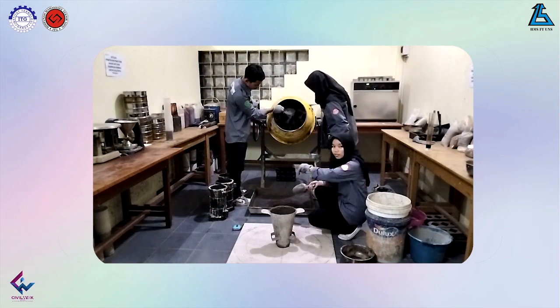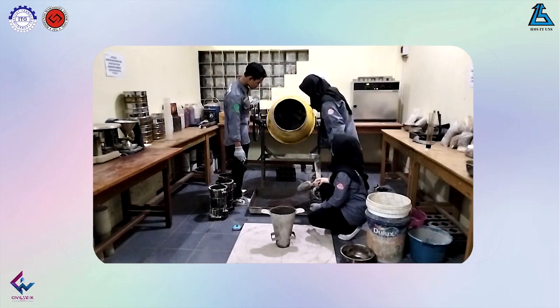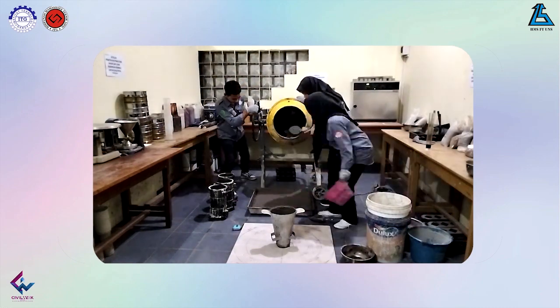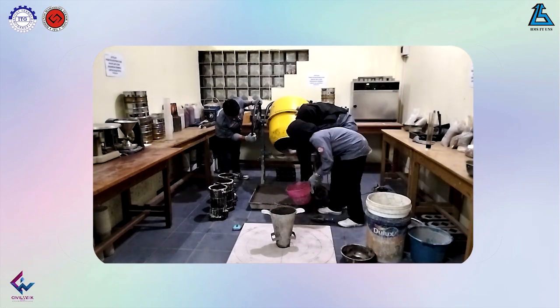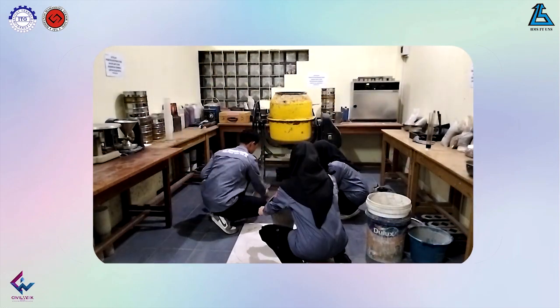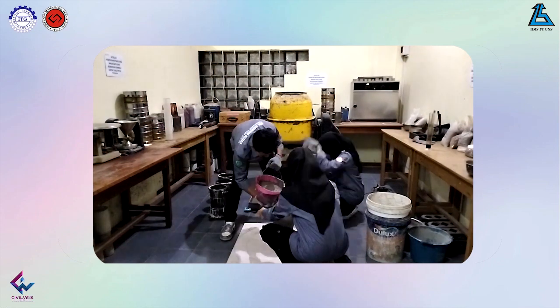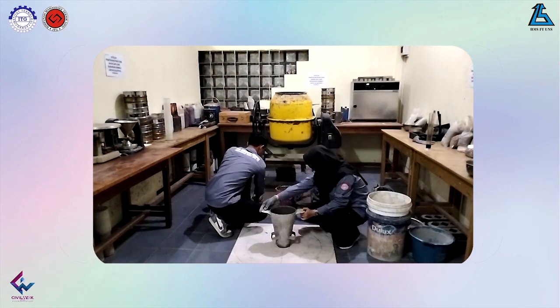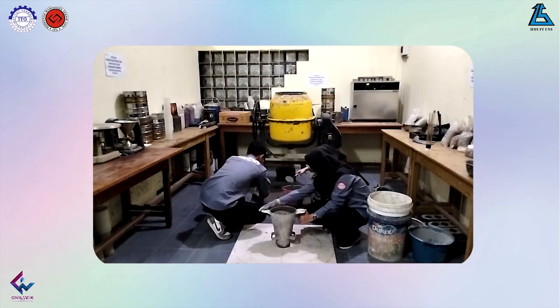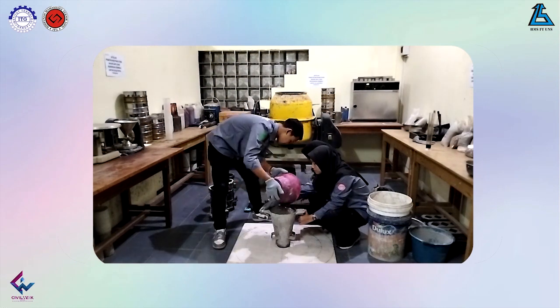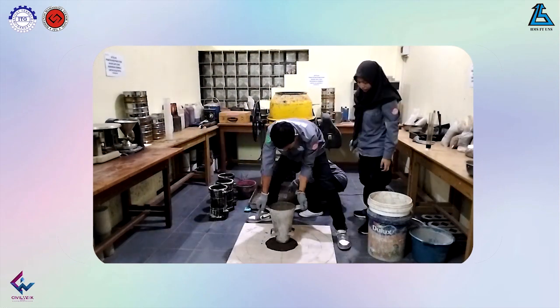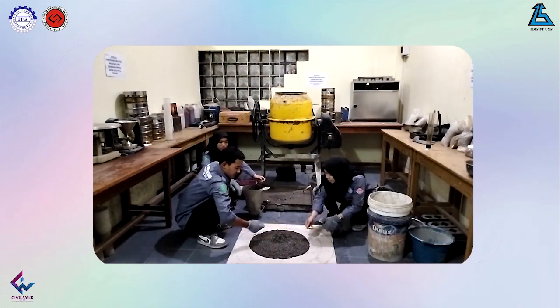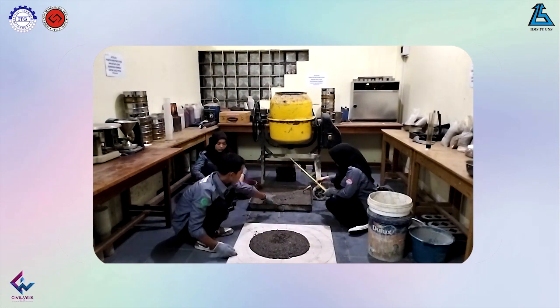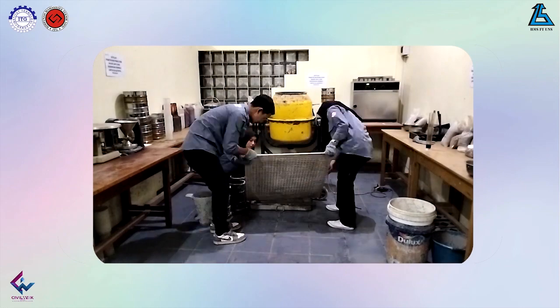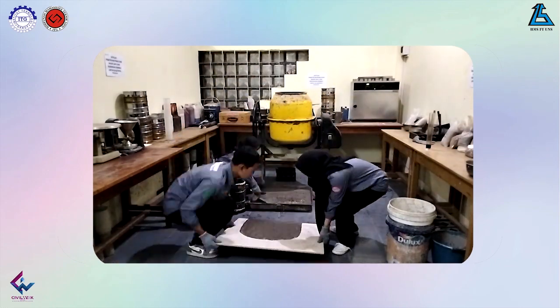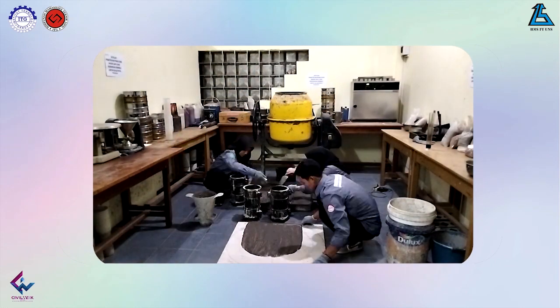And slowly add 4.23 kg of water. After the water is all in, allow 30 to 60 seconds until the water dissolves and mixes with the other ingredients. Finally, enter the admixture into the concrete mixer, as much as 0.12 kg. Next, the concrete mixture is poured into the concrete pouring place.